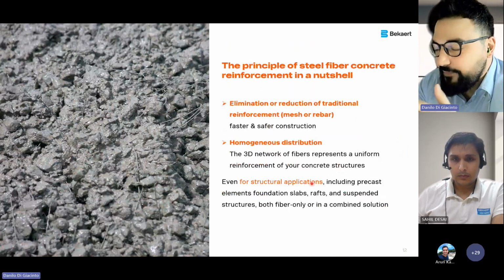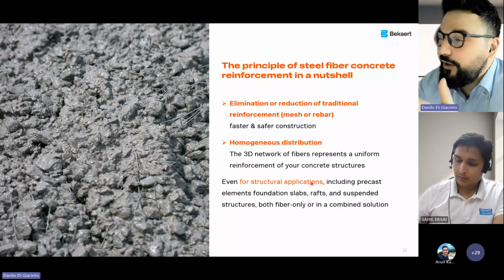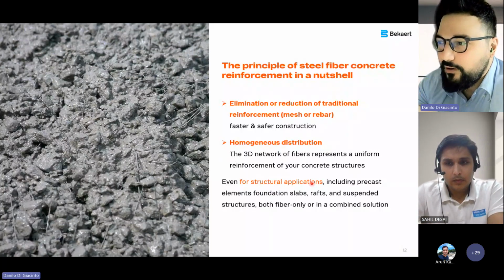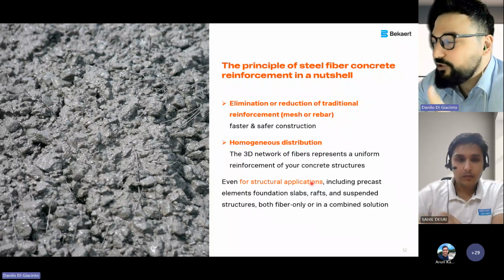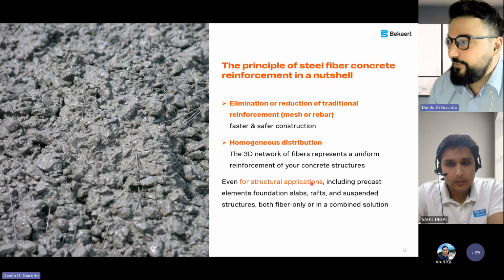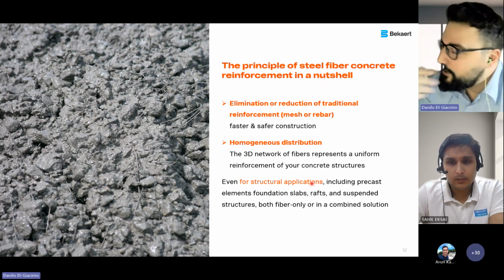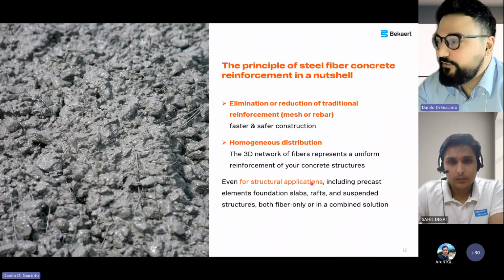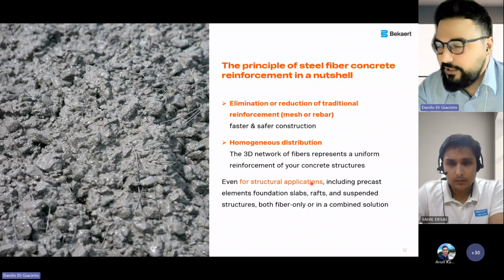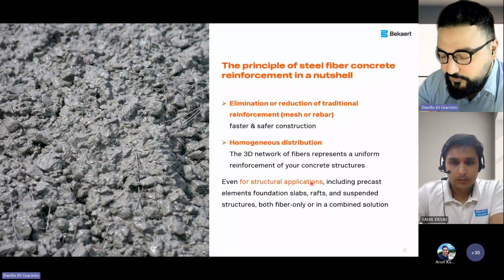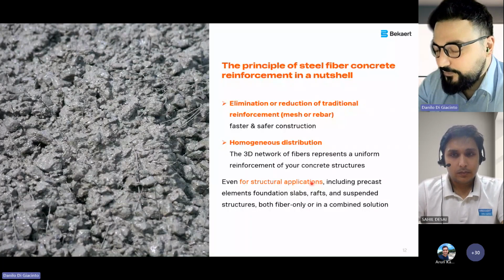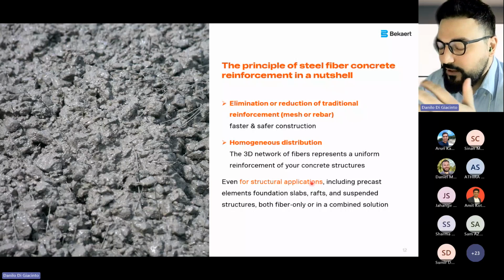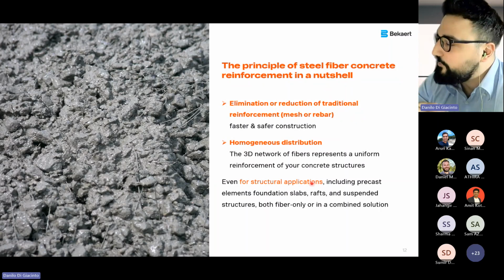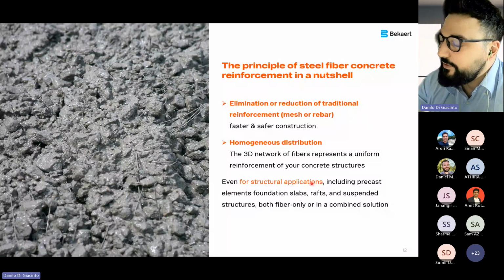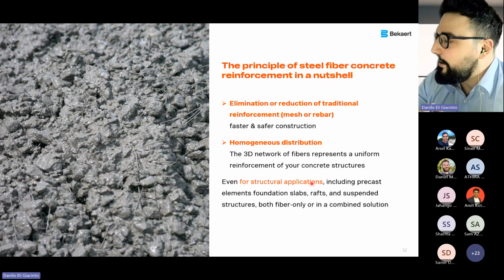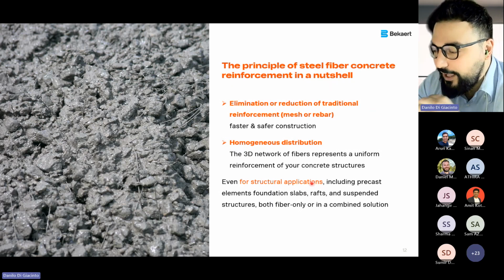What happens when you add fibers to your concrete? Being a reinforcement for your concrete, you can eliminate or reduce the traditional reinforcement in the form of mesh or rebars. So you can have either a faster and safer construction, actually both the features you can achieve. You can have a homogeneous distribution because the 3D network of fibers is a uniform reinforcement in your concrete structures. So, for example, specifically for precast, spalling, the presence of part of concrete which is not reinforced, which can lead to problems in the aesthetic of your precast element, can be avoided. So you have an element which is reinforced in every point.